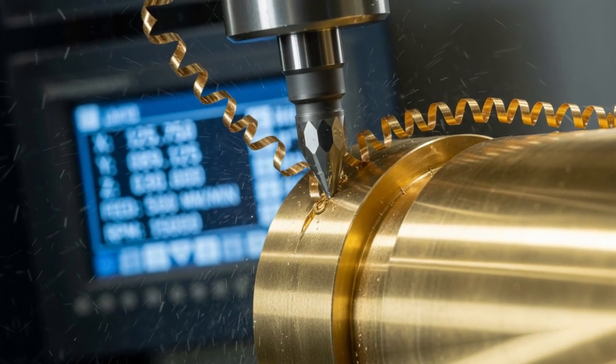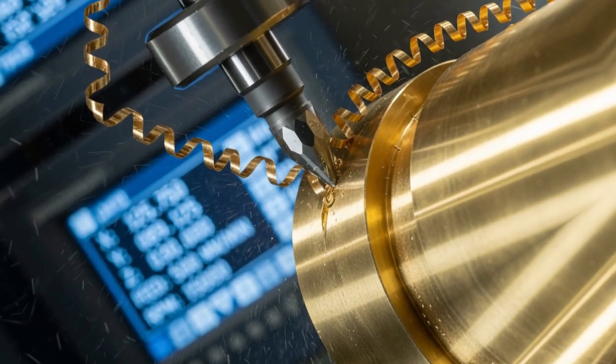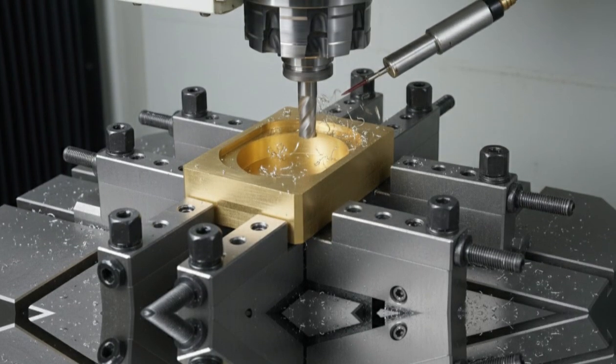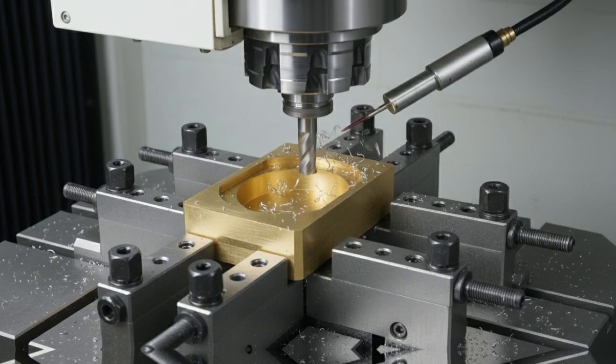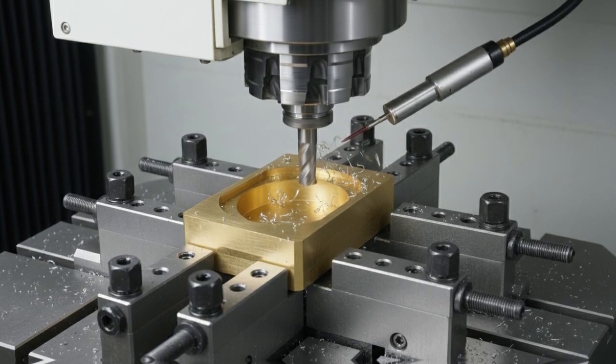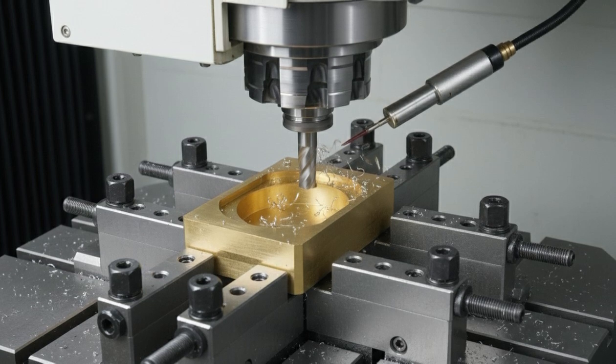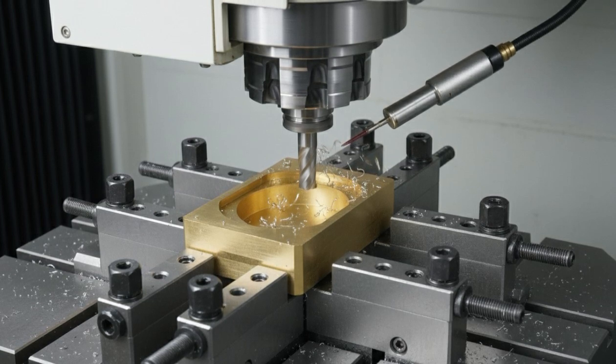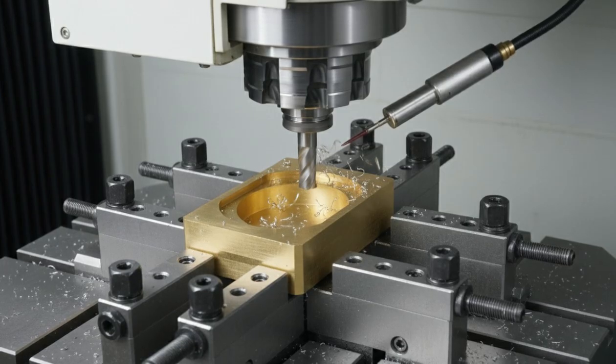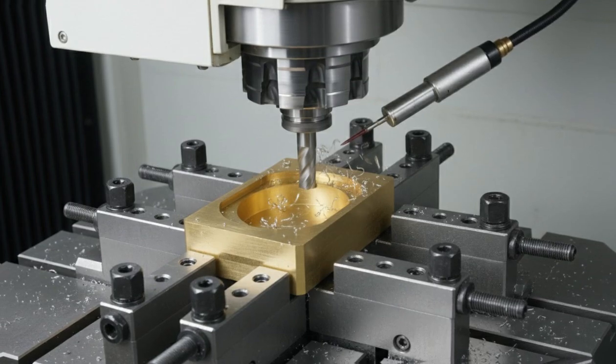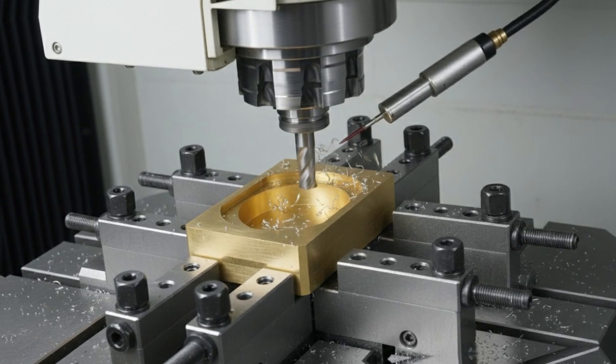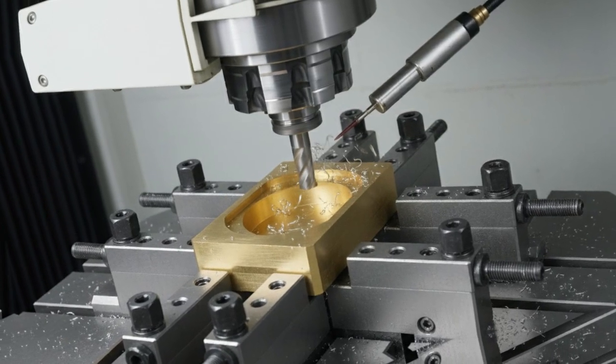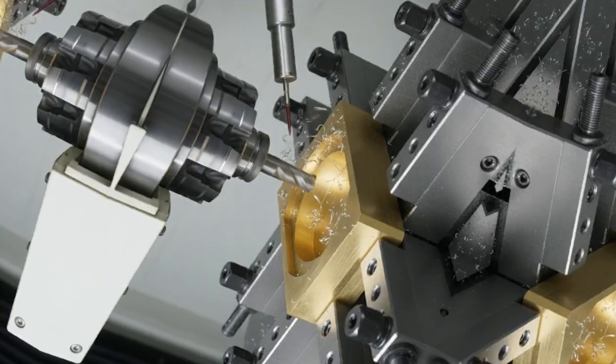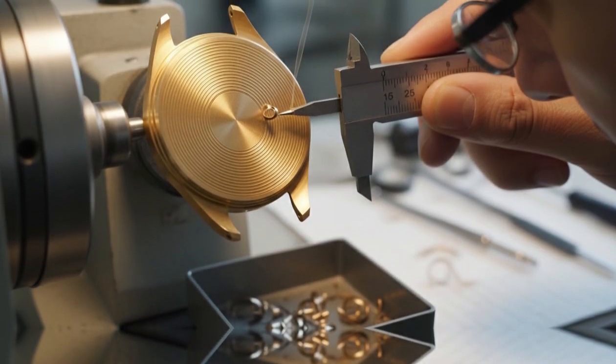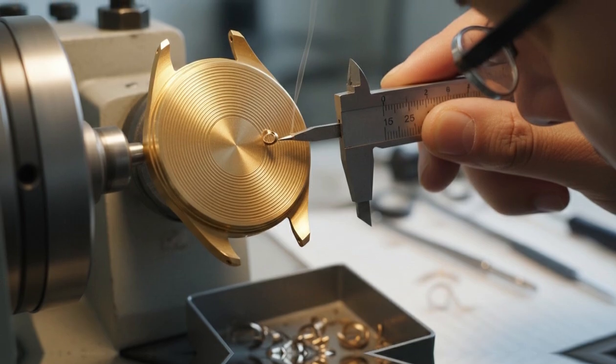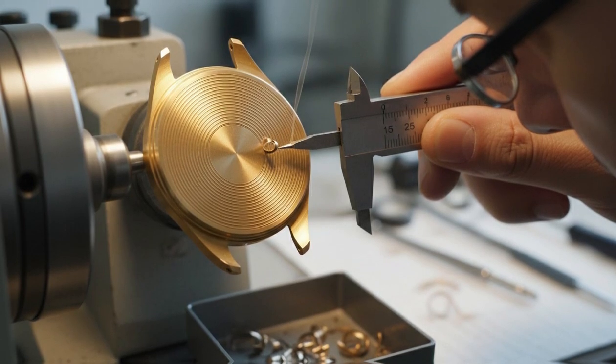The properties of the final alloy, its color, hardness, scratch resistance, corrosion resistance, and machinability, depend not just on what elements you add, but in what proportions, in what order, at what temperatures, and how you cool the mixture. Change any variable, and you get a different result. Rolex's yellow gold alloy, for example, is 18-karat gold mixed with specific proportions of silver and copper. The exact ratios are proprietary, but the result is a rich, warm yellow that's slightly deeper in color than standard 18-karat yellow gold. More importantly, the alloy is harder and more scratch-resistant, while still maintaining the workability needed for the complex machining operations that will shape it into watch cases and bracelets.